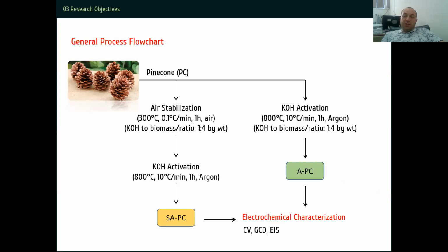In our study, we select pine cone as a biomass source. First, the pine cone samples were subjected to thermostabilization at 300 C at a heating rate of 0.1 C per minute in air environment. Then we chemically activated the resulting material with KOH. To see the effect of thermostabilization, pine cone samples were directly activated with KOH at the same conditions. We marked the samples as SAPC and APC respectively, as you see in the slide.